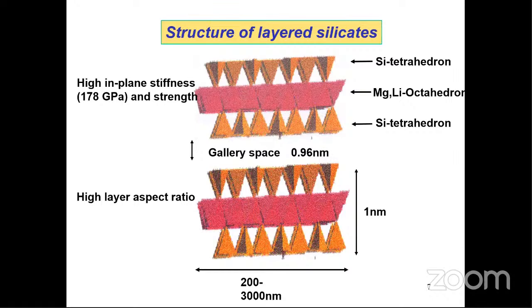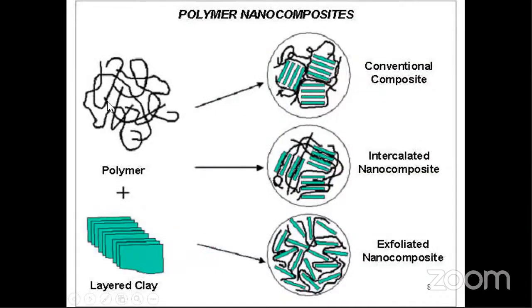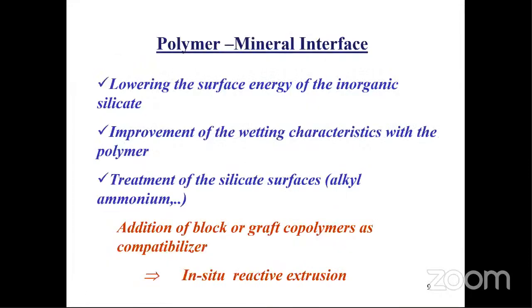Let us look at the clay system. We've been very active in putting clay into polymer systems. I will show you some of our work on clay. This is a polymer system, this is clay. If you do very good mixing, you can get a beautifully exfoliated system. If the mixing is bad, you end up with a conventional composite. This is an intermediate situation.